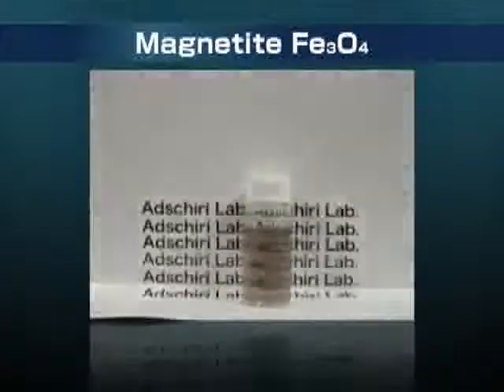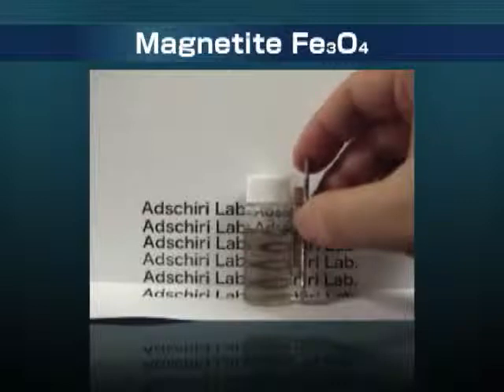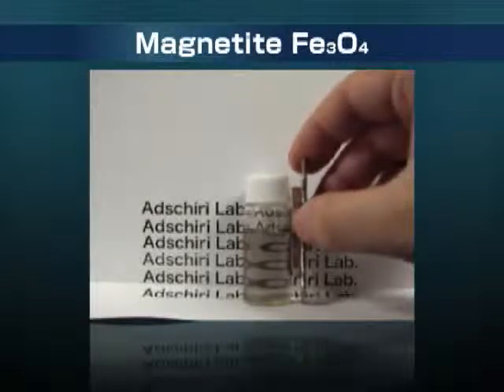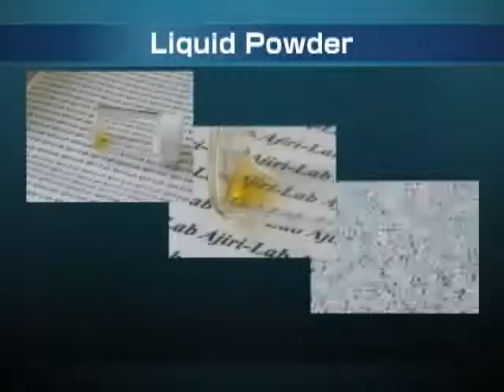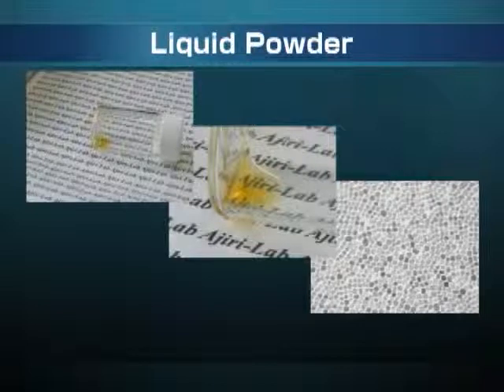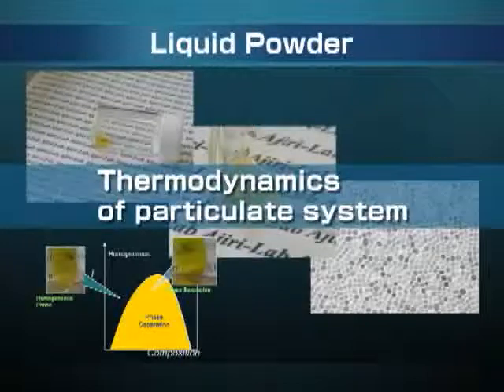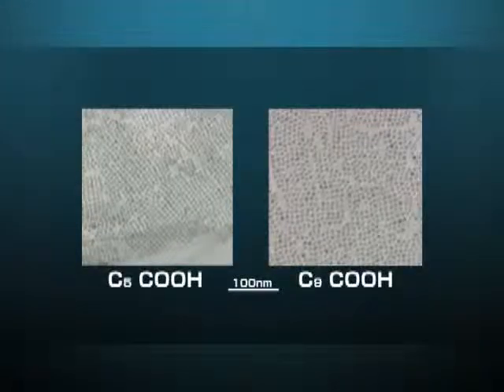In the solution, magnetic nanoparticles are dispersed. Is it true that particles exist in the solvent? Let's check using a magnet. We can see the particles gradually approaching the magnet — yes, particles exist in this solution. By evaporating this solution, we can concentrate the nanoparticle solution to make a honey-type liquid. So these organic-inorganic nanoparticles behave just like liquid chemicals rather than powders. Because the affinity between particles can be controlled, nanoparticles can be crystallized just like chemicals.